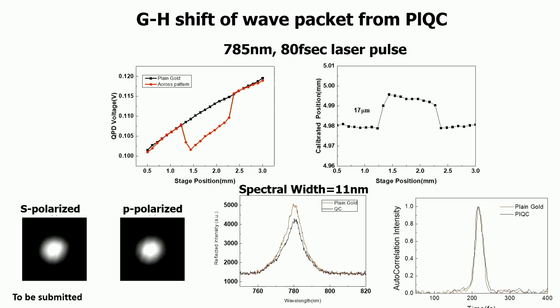The interesting point is that this is a broadband, dispersionless, launch angle independent and launch polarization independent structure. So though the plasmon mode is excited and there is a huge shift of about 17 micrometers in the centroid of the beam, the beam shape is undistorted, and even the spectral as well as the temporal widths, which are measured through autocorrelation, remain the same. So now we have structures where a complete short pulse can be coupled without any distortion, and we can make use of these plasmon-mediated effects.